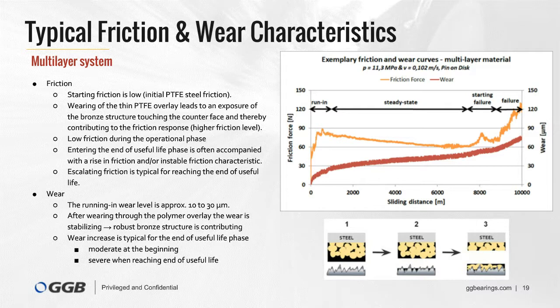During the operational performance phase, we have a low wear rate. Entering the phase of end of useful life is normally accompanied by a moderate increase in wear, and at the end of useful life phase, we normally see an escalating wear development.